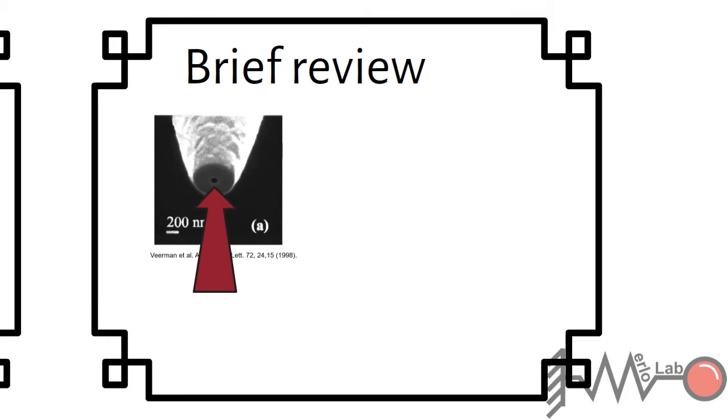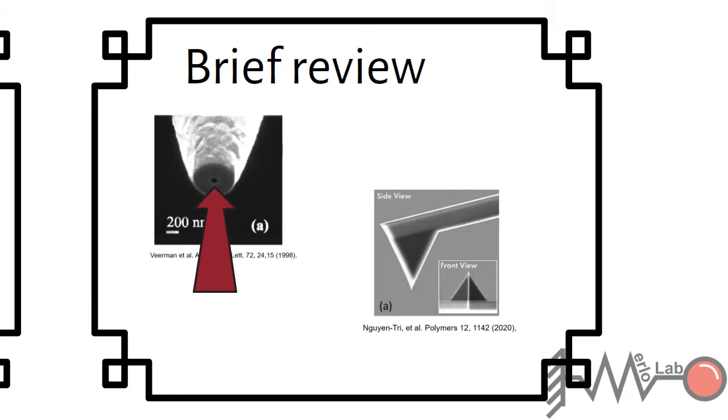The detection scheme in these probes is made far away from the sample by locating a photodetector at the end of the optical fiber. The apertureless, or scattering probes, are usually silicon AFM tips that are coated with a metal film to enhance their scattering cross-section. In these kinds of probes, the illumination and detection are made by free-space optical systems following a collinear path.